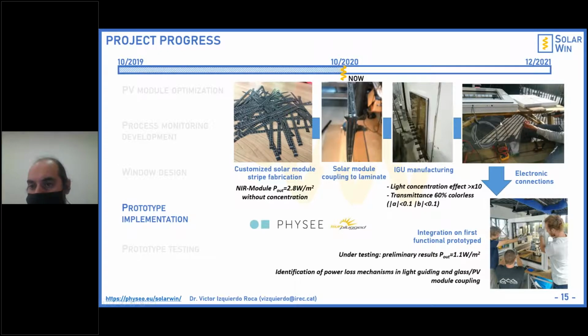Finally, we implemented these glasses inside of the frame, coupled with all the electronic connections, and implemented the first window. Here you have a picture of the first prototype, the functional prototype that we tested. In preliminary testing, we obtained 1.1 watt per square meter, but take into account that these conditions are without any control, measuring directly with the sun, but without controlling the radiation and without aligning well.